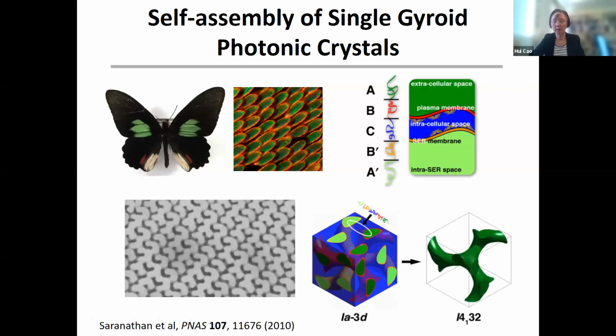It seems like what they do is they start with a lipid bilayer film, and then they fold it to form a double gyroid structure, and then a protein called chitin is deposited on the cellular membrane. And when the cell dies, this membrane will be replaced by air, and that leaves us the single gyroid. So you see, this actually is a pretty smart method, because we know the double gyroid is easy to assemble through self-assembly. But a single gyroid structure has superior optical properties.